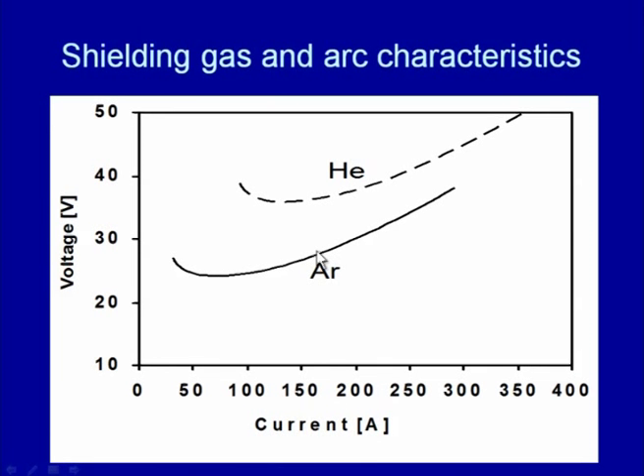And because of these reasons, helium is preferred under certain conditions when either the thickness of the sheet to be welded is high or the thermal conductivity of the metal to be welded is high as compared to that of argon. If we see the VI characteristic curve of the GTA process, where in one case we are using helium and in another case we are using argon, the helium invariably results in a higher arc voltage than argon when argon is used as a shielding gas, and this difference is mainly attributed to the difference in their ionization potentials.